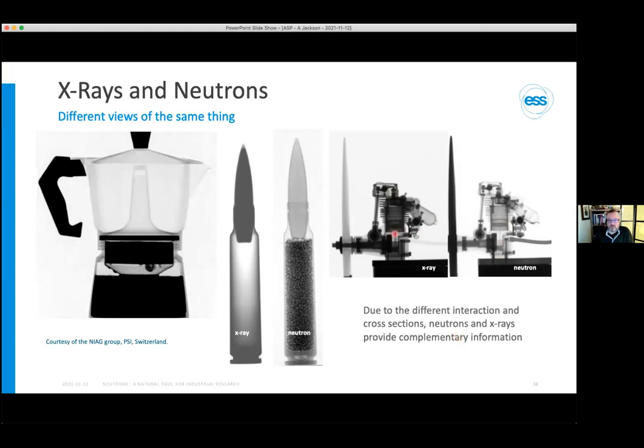Looking at an engine with x-rays, we primarily see the metallic outer shell, whereas with neutrons the aluminium is more transparent and we can see through to the steel components and plastic components inside. With a rifle cartridge, the lead, copper, and brass are very non-transparent to x-rays due to their high atomic number, whereas for neutrons they have relatively low cross-sections and end up being rather transparent — allowing us to see the grains of gunpowder within the structure. By combining x-rays and neutrons, we get a better picture of our sample system.